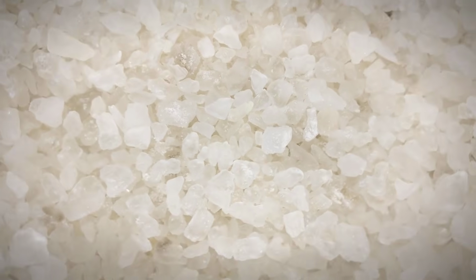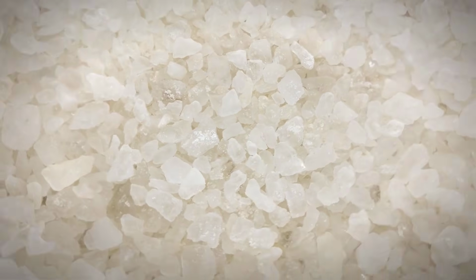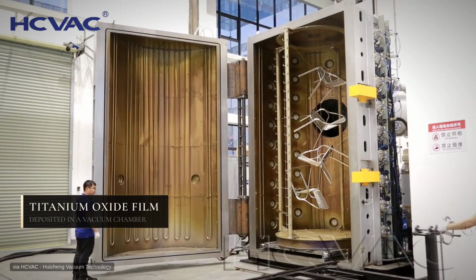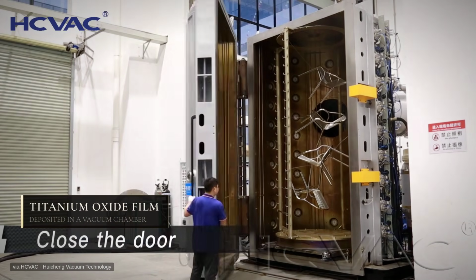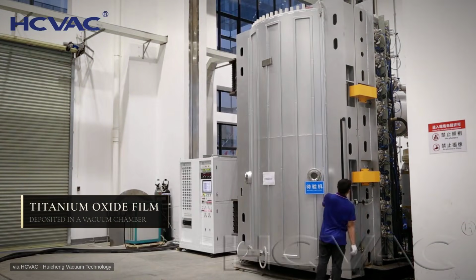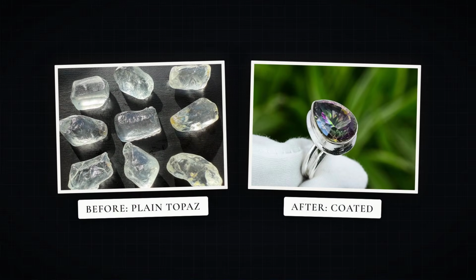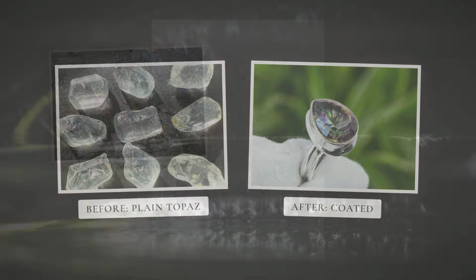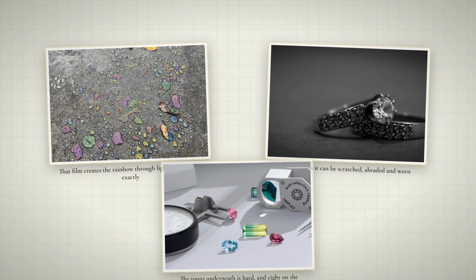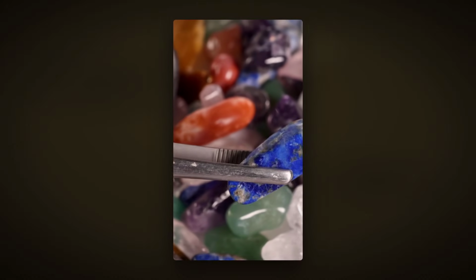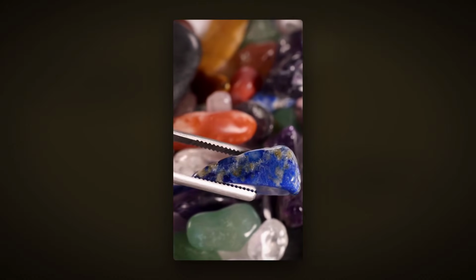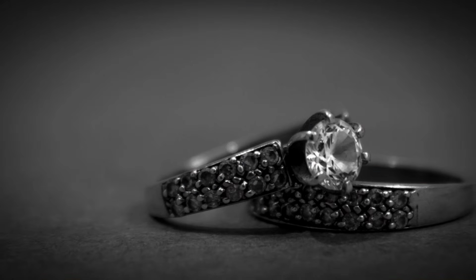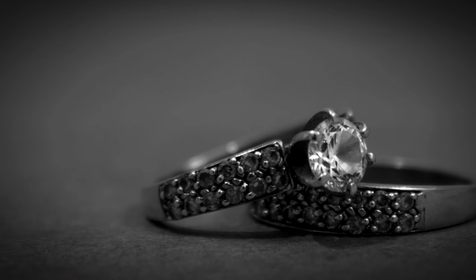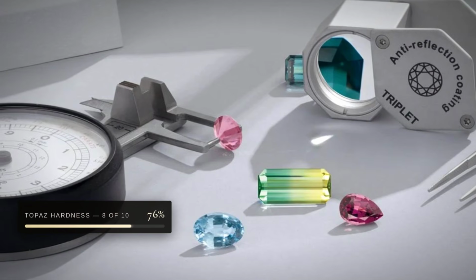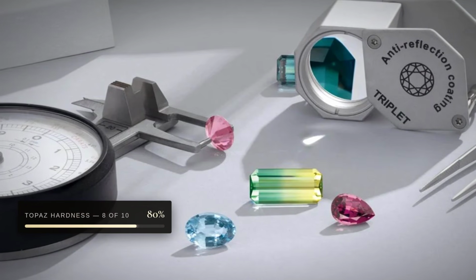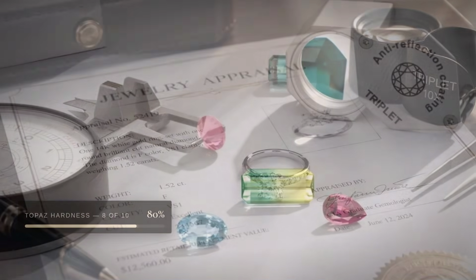It starts as ordinary colorless topaz, which is cheap and abundant. Then an ultra-thin metallic film, usually titanium oxide, is deposited onto the surface in a vacuum chamber. That film creates the rainbow through light interference, exactly the same physics that makes an oil slick shimmer on a puddle. 2 things follow. First, the color is on the outside, typically on the underside of the stone, which means it can be scratched, abraded, and worn through. The topaz underneath is hard, an 8 on the hardness scale, but the coating is not the topaz.